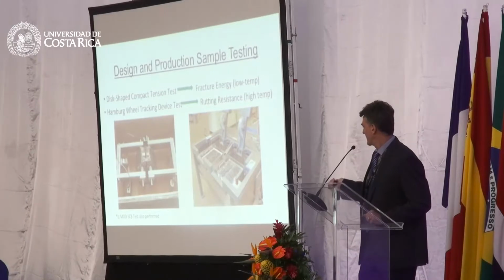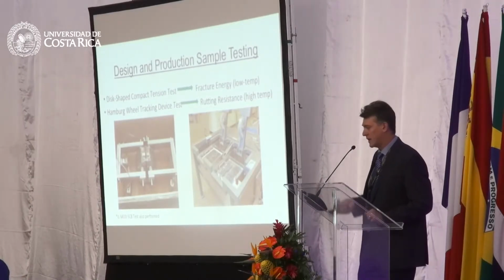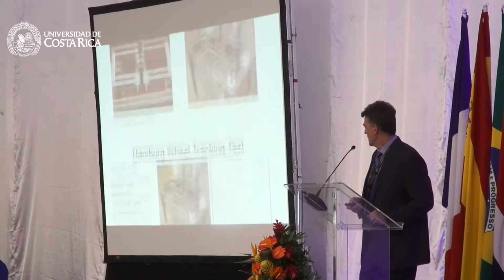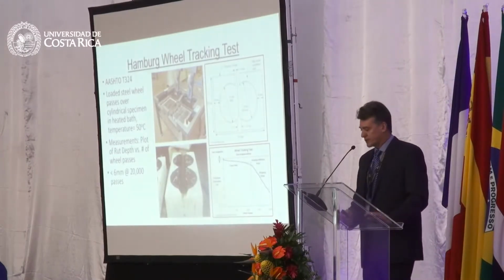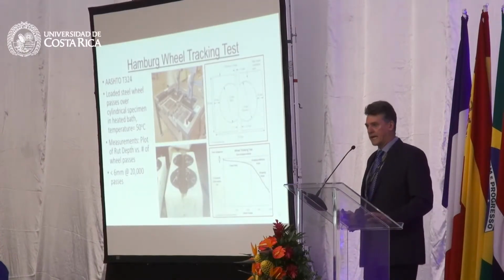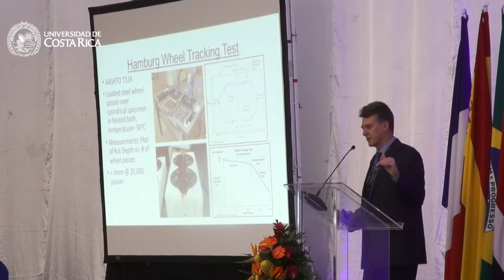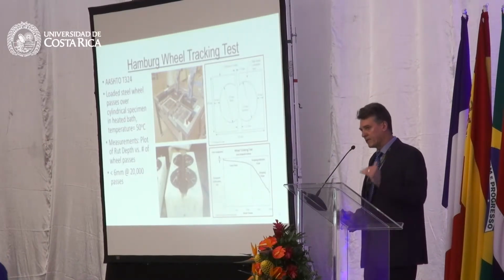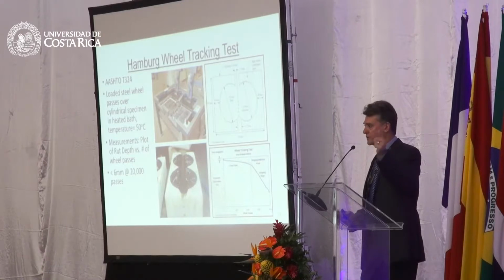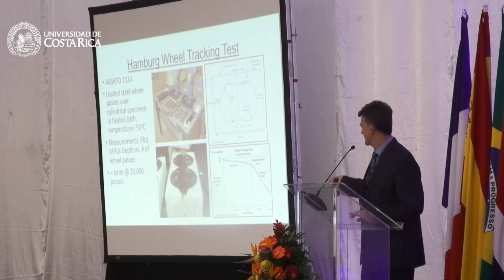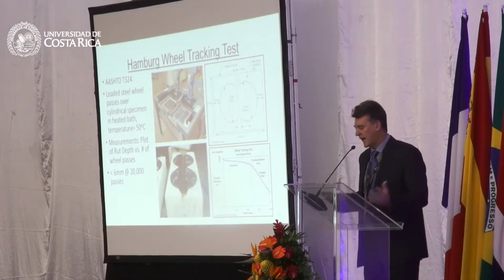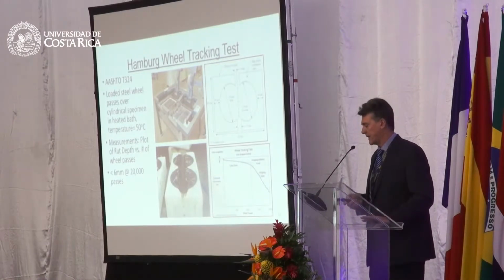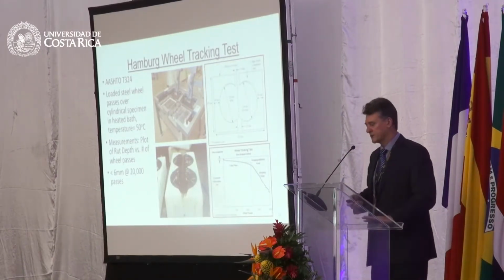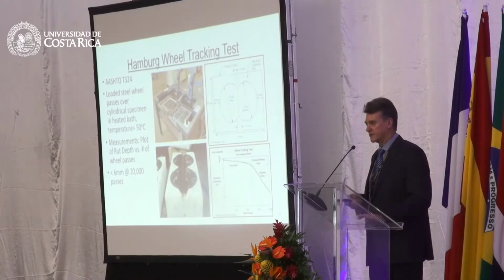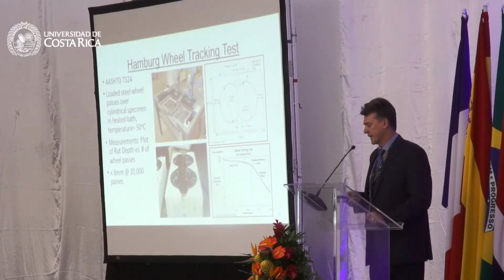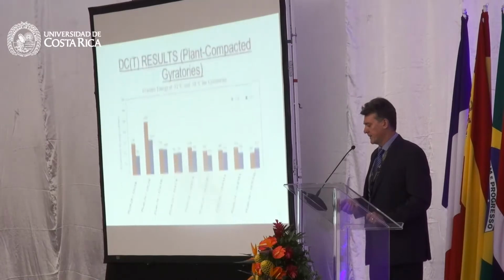And so we ran the low temperature cracking DCT test, the Hamburg tests. The Hamburg wheel tracking test, we followed a lot of the guidance out of Texas. We used a fixed temperature of 50 degrees Celsius, and for higher traffic levels, we use higher number of wheel passes. In this case, we used the highest typical number used, which is 20,000 wheel passes, and this was also done submerged. In case there is a propensity for moisture damage, we wanted to be able to capture that.